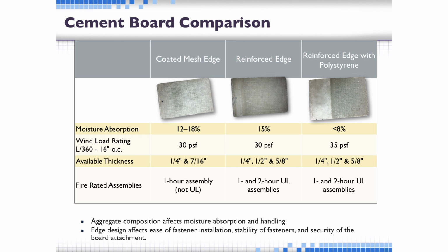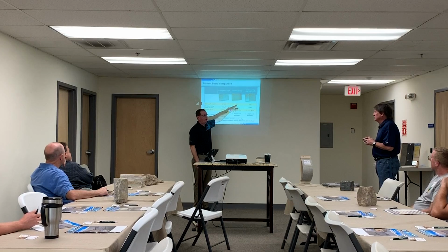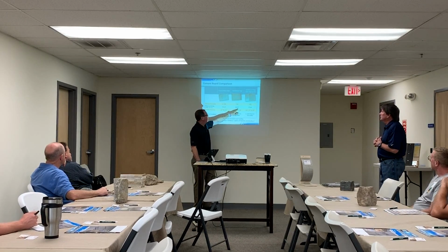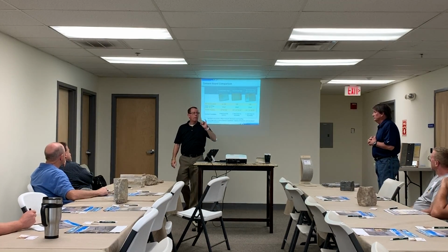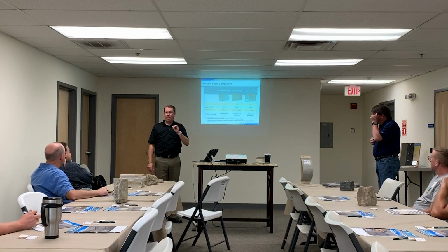So the most important thing for our discussion today is water absorption. There's several reasons for that, so that's our first line item. So Wonderboard 12 to 18%. So cement, it sucks up moisture, right? It's just going to do that. Durock, 15%, I believe, they report maybe 12% now, something in that range, so I should probably change my number to 12% for Durock. And then we're 8% because of those expanded polystyrene beads. They don't absorb moisture, so we don't absorb it as much.